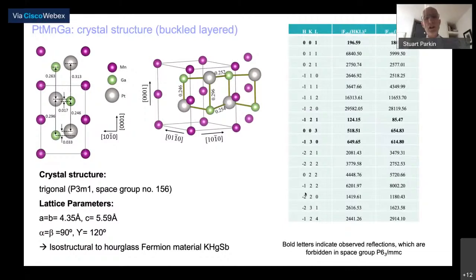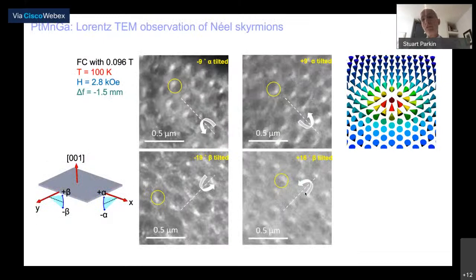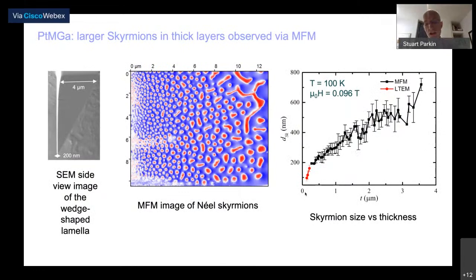And in this structure, we've discovered, again, for the first time in a metallic compound, a Néel skyrmion. As I mentioned earlier, in the Lorentz micrograph, we cannot see these structures when the beam is exactly perpendicular to the lamella in which we observe them. We have to tilt the sample, and then we can observe. I think you can see very faintly in this structure these Néel-like skyrmions, and this shows you the same material observed by magnetic force microscopy, and then we can see beautifully the out-of-plane component.